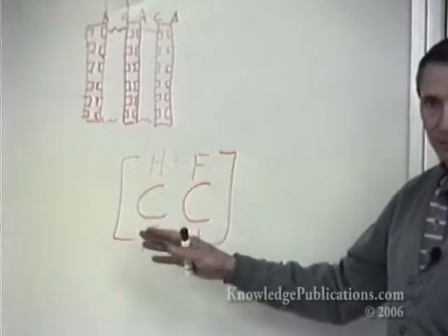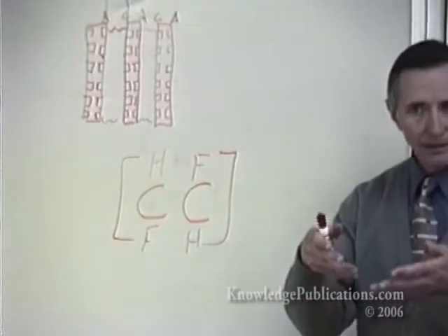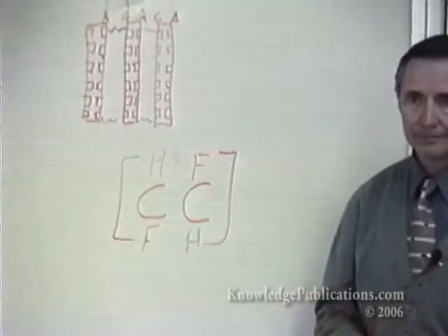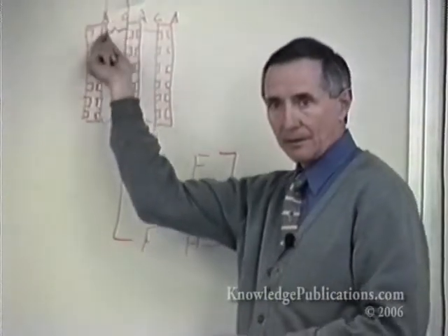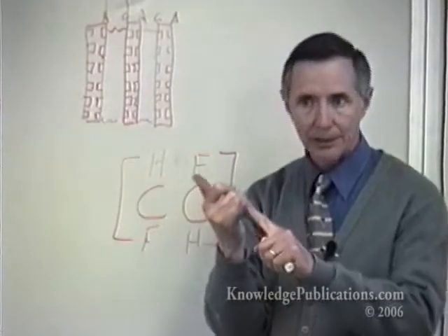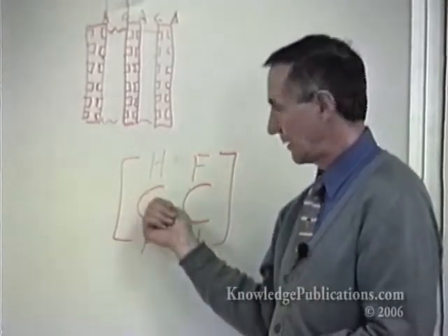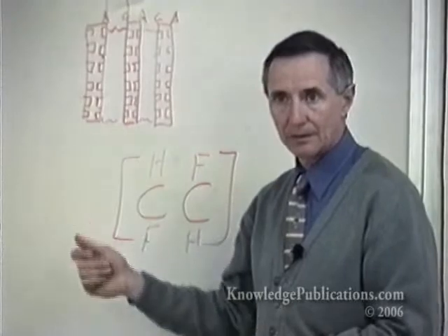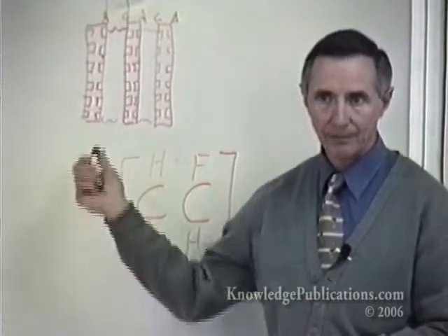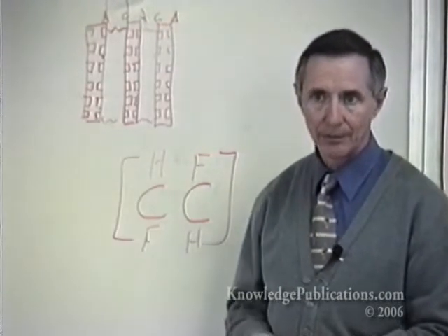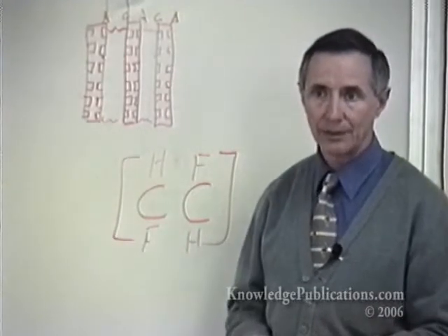more solvent susceptible material, so that you can mix this substance with carbon black and very finely divided platinum. Deposit it from a solvent so you get a very thin layer of material that has the properties of divorcing water, rejecting electrons, but readily accepting the ion that you want to produce in your fuel operation, in your fuel ionization and ion entry into the semi-permeable membrane. So that's a very good thing to do. That's one area that Ballard and others are working on.